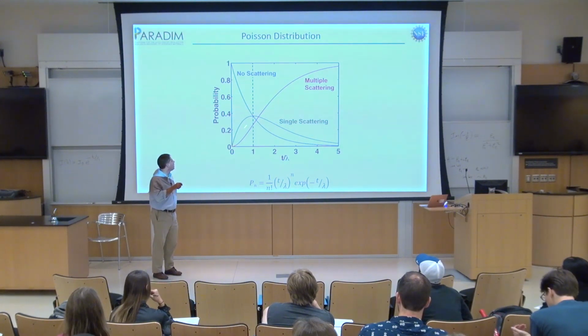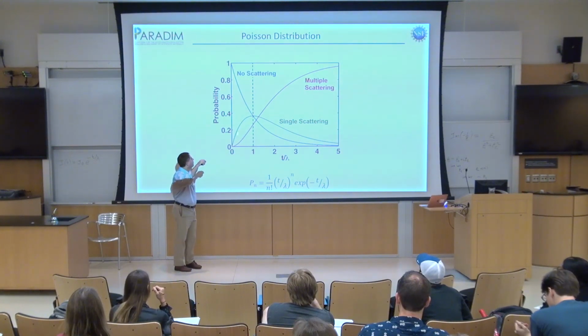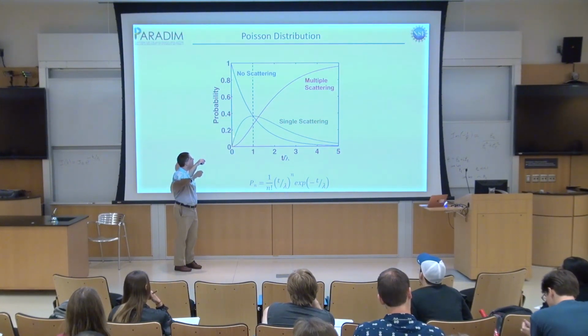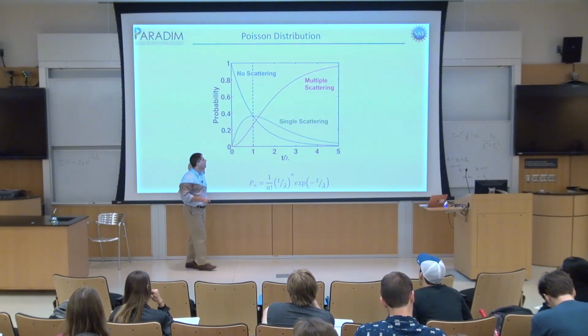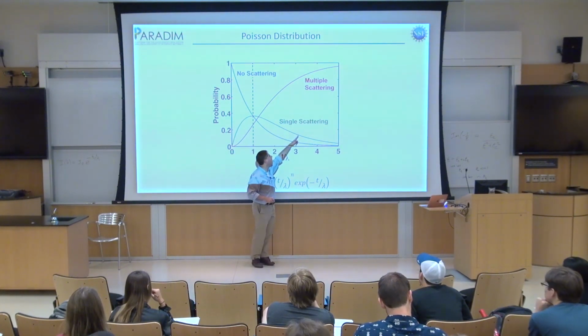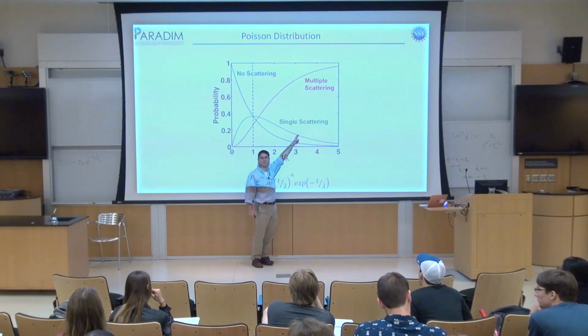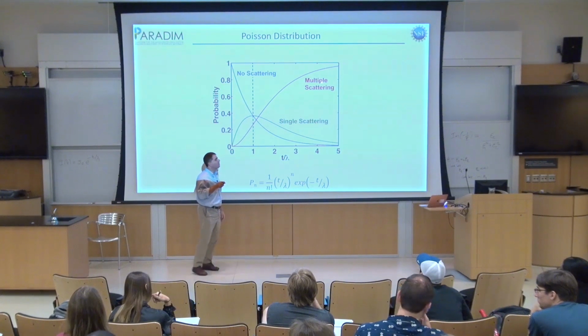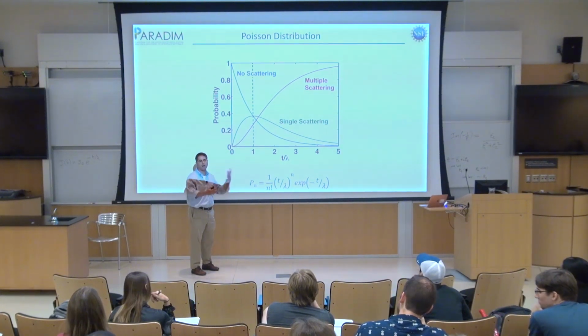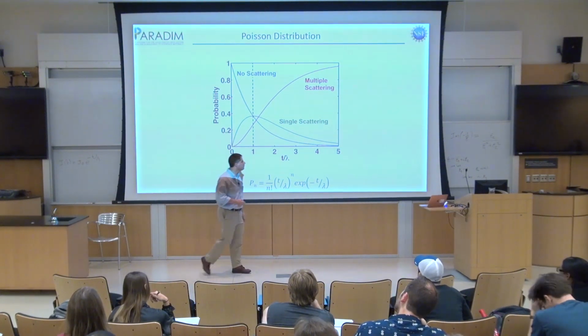You might want to be working thinner than that. Over here, the peak to background ratio is really good. So this is where you'd like to be, but hey, we can live with this regime as well. There's still pretty healthy single scattering out here at 3 mean free paths. And the nice thing is the multiple plasmon scattering is at a higher energy, so it's not going to overlap and mess with our signal.